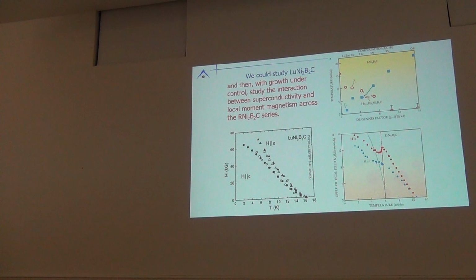So we could study lutetium nickel 2 boron 2 carbon. Here's the 17 K TC. It has a mildly anisotropic Hc2. It's not a very large Hc2. This is not going to be a practical superconductor. On the other hand, given that you could have it for lutetium, you can substitute in other moment-bearing rare earths. So you have lutetium or yttrium, but you also have thulium, erbium, holmium, dysprosium. For all of these materials, you have Tc, but for the thulium through dysprosium, you also have T-Neel, and you can look at the interaction of magnetism and superconductivity. You can see Hc2 respond very strongly to the onset of magnetic order. There's a lot of neat physics you can play around with.